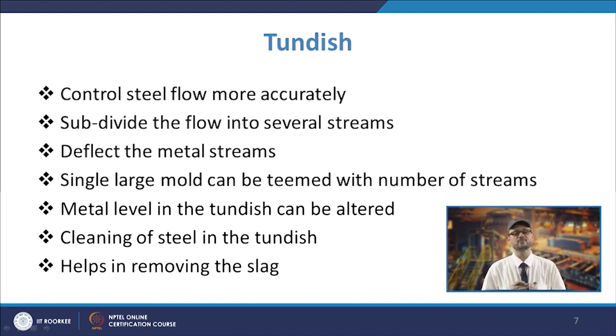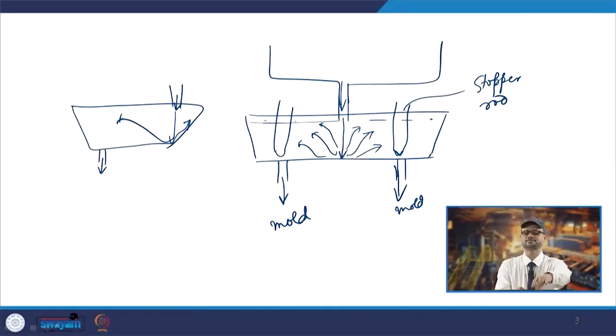Now, it will also help in removing the slag, because if there are slags, they will be floating at the top. If the slags are entrained, because of the flow coefficient inside which can be maintained, you can allow these slags also to float. In normal circumstances the slag will be at the top and beneath that there will be molten liquid. So, we also get the help in removing the slag. Because the slag will be at the top portion and we are taking the liquid from below, liquid metal is drawn from here and delivered to the mold from here. So, anyway that slag does not cause any harm.